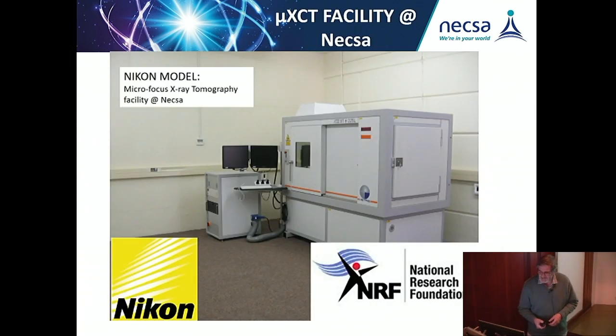The resolution you achieve from these machines is a direct function of the spot size of where the X-rays are being generated from. Through geometric enlargement, you end up eventually, if you have a smaller sample, projecting it on the larger detector, and that larger detector pixel size is 200 micrometers on an array of up to 2048 by 2048 pixels. So this kind of machine is now located at Nexa, and some of you in the audience already utilized this machine.